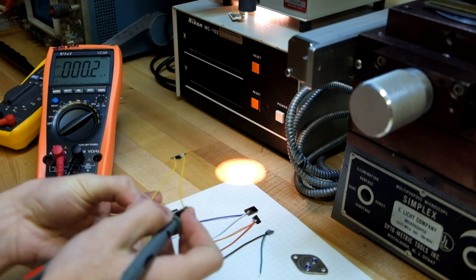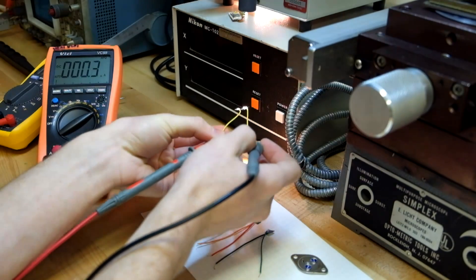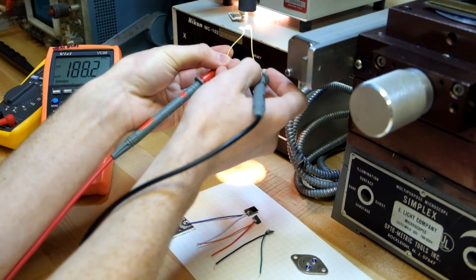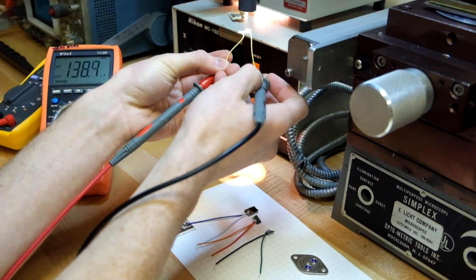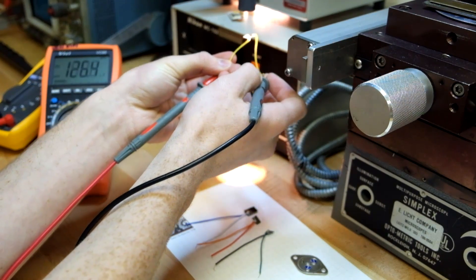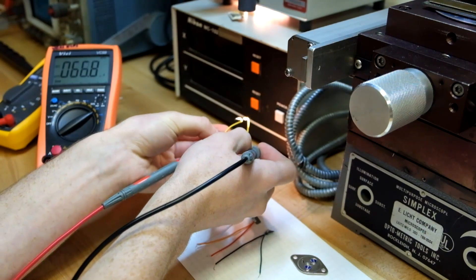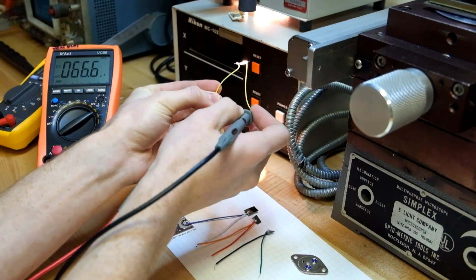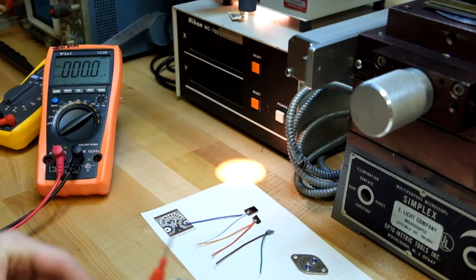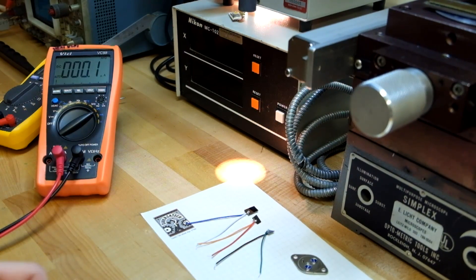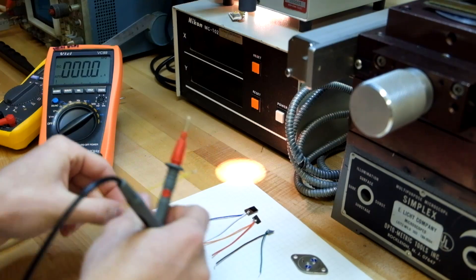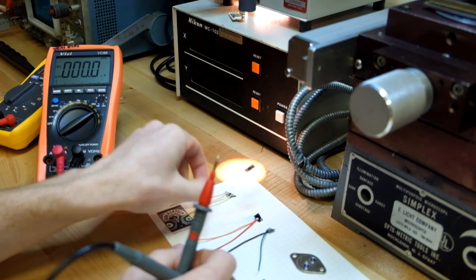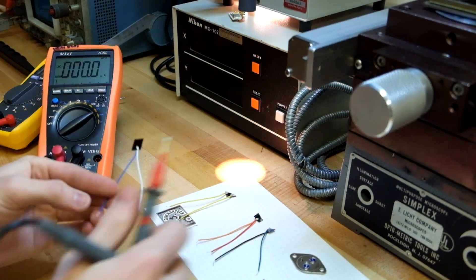So, we have 0.1, 0.2 of a microamp in ambient lighting. And I'll put it onto the intensified light. And that's quite a lot, actually. 250 to 200 microamps at that quarter of a volt is not bad at all. The efficiencies of these are on the order of 1 or 2%.